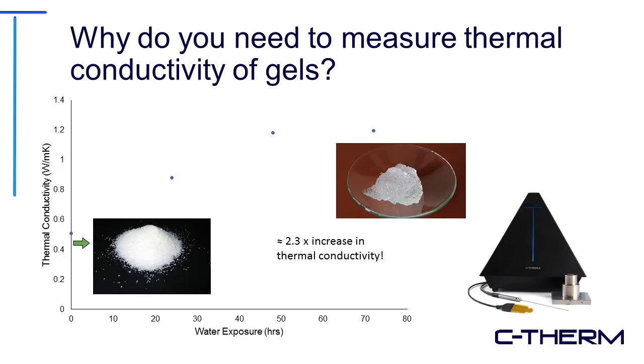So that's exactly what we need to do. This is thermal conductivity of some polymer type materials. You can see here at the beginning the material that we worked with, which was sodium polyacrylate, in its dry state has a thermal conductivity around 0.5, whereas as you expose water to it, as we swell these types of materials up, we can get an increase of up to 2.3 times the thermal conductivity, which is exactly part of the reason why we need to measure these types of materials in the biological system that we're going to be accessing, because swelling of these polymers can effectively change thermal conductivity. So it's important not to just trust bulk values of these polymers, but to actually go out and measure these thermal properties of these materials themselves.